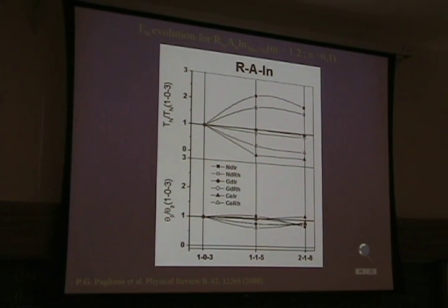And cubic, bilayer, single layer, they all have the same Néel temperature. Okay, when you go to neodymium, it does change. It increases for the tetragonal compound, and for cerium, it decreases when you go from cubic to tetragonal. So both have crystal field, but cerium additionally has the important role of hybridization, in common.